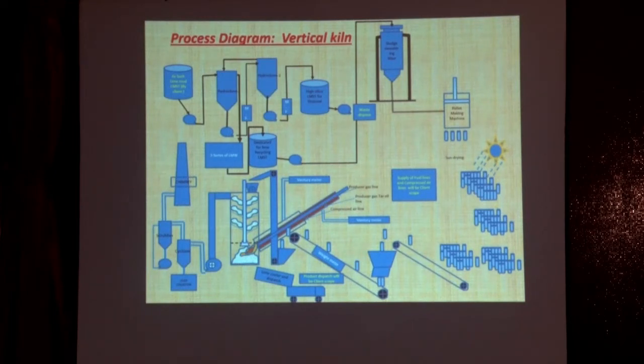By a one-stage centrifuge system, we reduced the silica content to 3.5% in a single stage. And our aim is to reduce the silica content to 1.5%. We know, after a lot of discussion and research, that the density of calcium carbonate particles and the density of silica are very close. But silica has a size larger than the calcium carbonate particle, and we have been successful in reducing the silica content to 3.5%. We are pretty sure that even at 3.5% we can run the rotary lime kiln, no issue. Usually people are producing 80% purity. Even some mills with 3.5 to 4% silica are getting approximately 80% purity consistently.